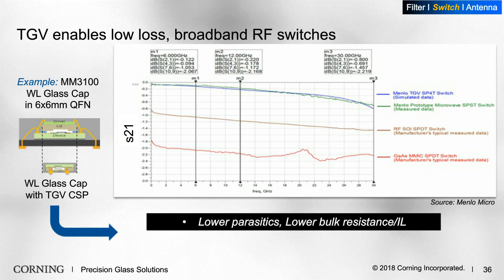So this is where a glass encapsulation is one of the first steps that you would take at realizing the product. But the product itself is actually a system in a package. It needs actuation, ASICs, and other elements. And as a result, it's already a 3D structure. And for that, you would want the smallest form factor. So hence the holes that support the cap and the substrate. And what we see here is that it's also very broadband.